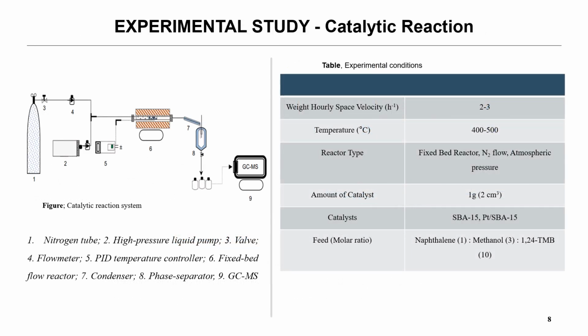The experimental setup of the study is as shown below. Methylation of naphthalene was performed at atmospheric pressure in a fixed bed reactor which consisted of a catalytic bed, a PID temperature controller connected to a heating source. The feed, consisting of 1:3 to 10 molar ratio of naphthalene, methanol, and 1,2,4-trimethylbenzene as solvent, was supplied using a high-pressure pump. For the tests, 2 cm³ of catalyst pellets were placed in the reactor and initially activated in a nitrogen flow at 500 degrees Celsius.